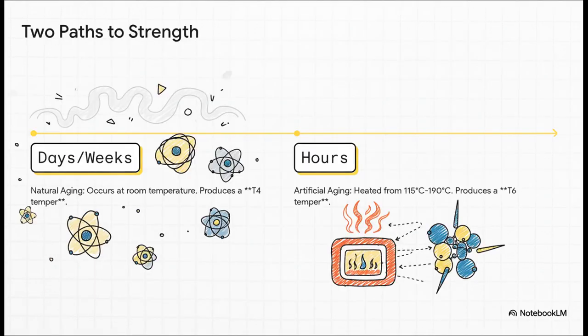And there are basically two ways to get there. The first is called natural aging. You literally just let the part sit at room temperature for a few days or even weeks, and it gets stronger all on its own. That gives you what's called a T4 temper. Or the much faster way is artificial aging. You gently heat the part for several hours, and that produces a T6 temper, which is usually the strongest the alloy can possibly get.